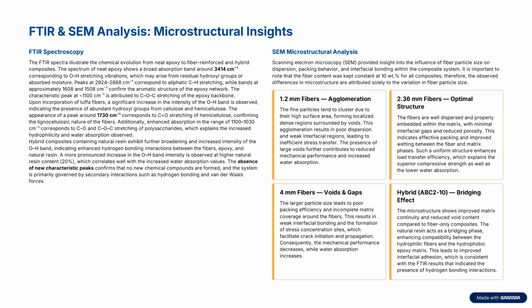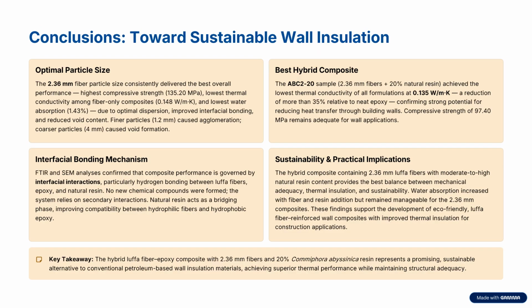For the SEM, we see that fine particles tend to cluster due to their high surface area, forming localized dense regions surrounding the voids. And also in the hybrid ABC2-20, the microstructure shows improved matrix continuity and reduced void content compared to the fiber composites. We conclude